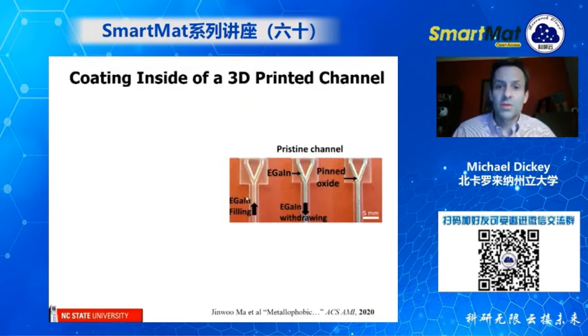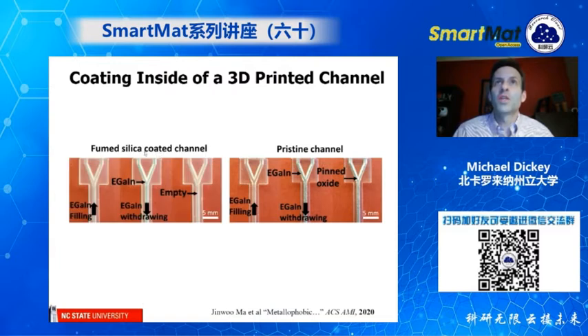So we did this on a 3D printed plastic, and we injected the liquid metal. So here's the liquid metal inside of this 3D printed part, and then we pull it back out, and you can see that if we don't coat the channel, it sticks. It's really difficult to remove it, at least remove all of it. But if we coat the channel, so this is silica coated, you can see we inject the liquid metal, and then we empty it, and no problem.